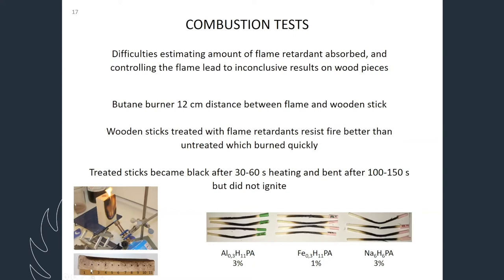We have a burner and we took a matchstick and we cut the tip off the top of the matchstick. We put the rod and below we put the flame at 12 centimeter distance. So untreated wood catches fire quite fast, but the treated ones are much better. The treated sticks become black after almost 1 minute and bent after an even longer time, but they actually never ignited.